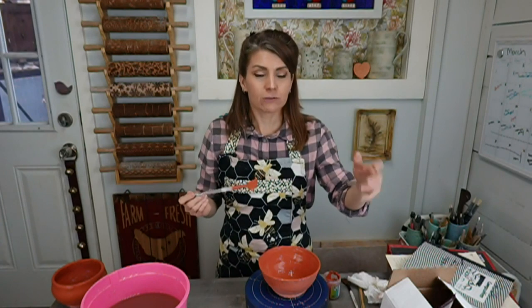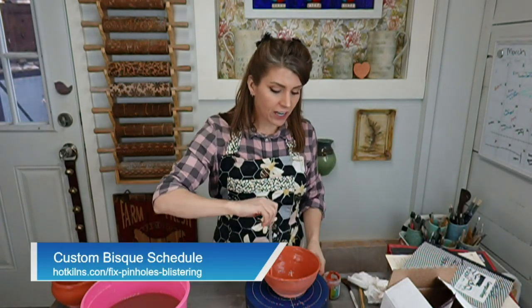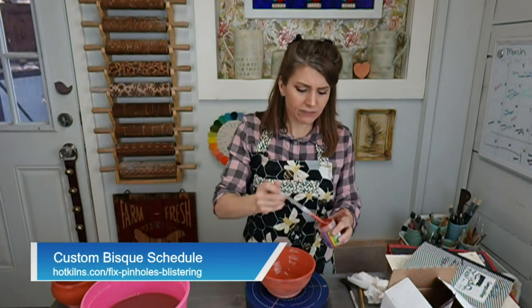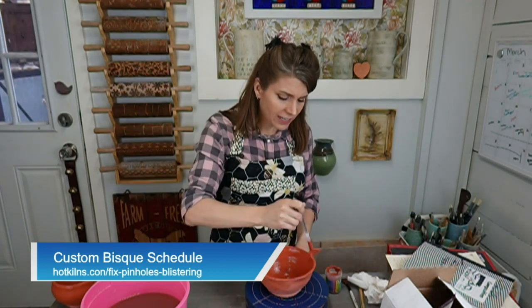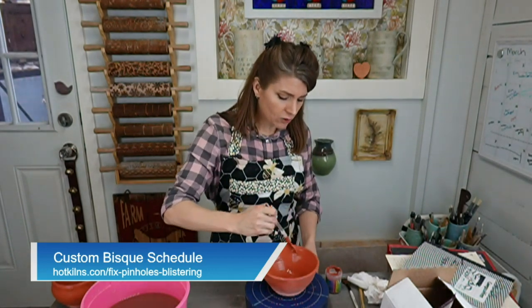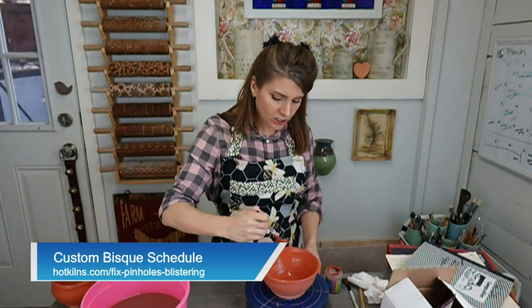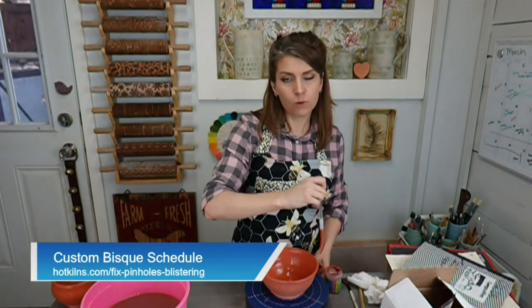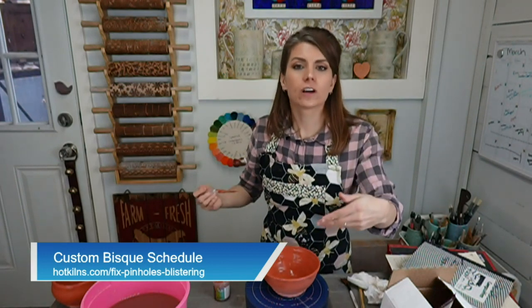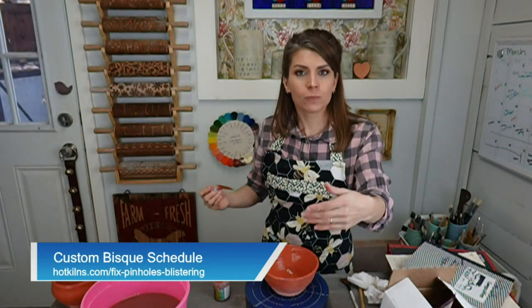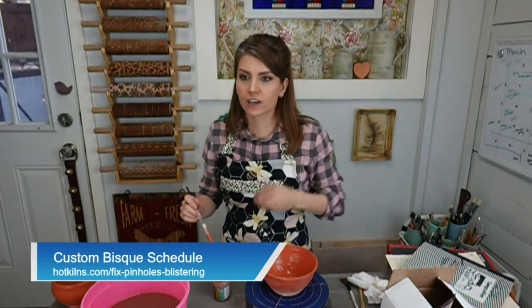And for me with my kiln, when I first got it, and that was in July, it was firing almost a whole cone hot. So I did a negative 35, I think it was a negative 35-degree cone offset, and I programmed that in so my kiln actually thinks cone 5 is cooler than it actually is, but it still fires perfectly because our heat work is what's doing the job, right? Our cones are melting, the glaze is melting, everything's working.